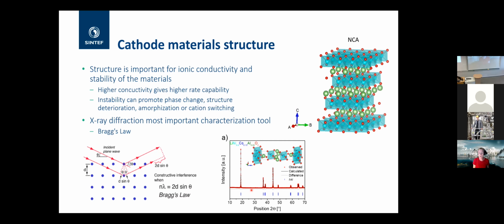planes in the structure. This particular figure shows the nickel, cobalt, aluminium with this specific composition, 80% nickel, 15% cobalt, and 5% aluminium. If you change up this ratio, these diffraction lines will remain, but you will start to see diffraction lines moving either to your right or to your left. So if you have a higher 2 theta value, so this big line moving down to your left, that means you're increasing the inner layer distance in your structure. And when you take lithium out of the structure, you will see often a decrease.